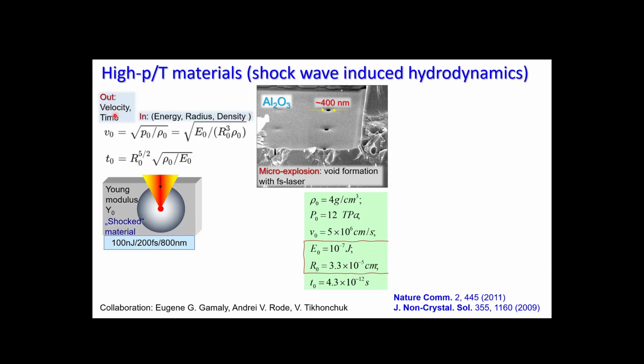The velocity of the shock wave, and the time when the shock wave is emerging from the volume where energy is deposited. You need to know the energy deposited, and you need to know the geometry, the radius of the deposition volume, and the density of your host material. So these are simple expressions. Let's have a look at this 100 nanojoules focused into a spot with a radius of 330 nanometers, finally producing this type of void. So energy in volume is the same as pressure by definition: joules per cubic meter is newtons per square meter, so this is pressure.